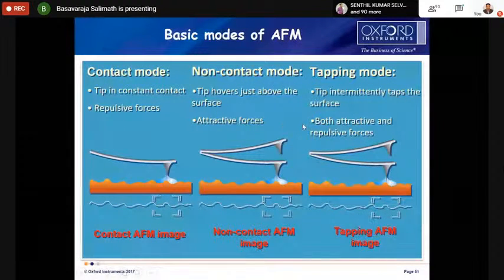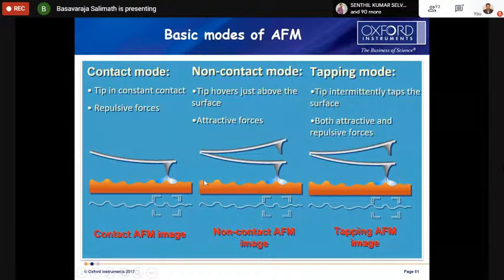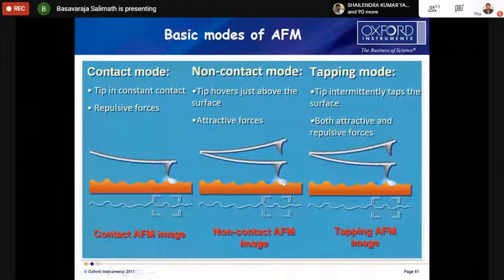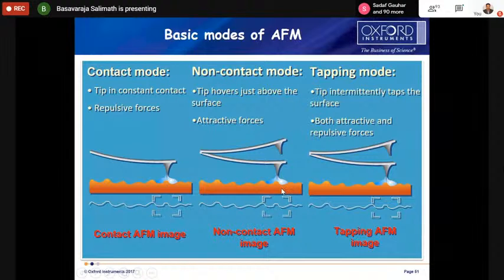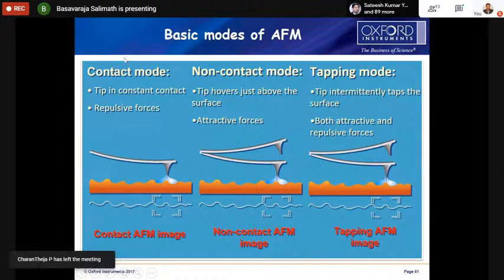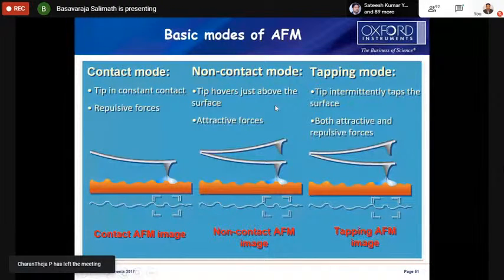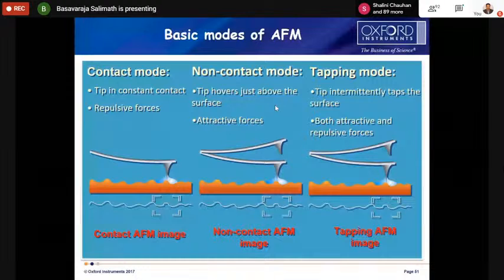Whereas in case of non-contact mode, the tip will not be touching the sample; it is maintained a little bit above the sample. So if we have some kind of water layer on the surface, we are actually getting the image of the water layer. Okay, so not the surface actually. That is one drawback of this non-contact mode, and that's why people mostly use tapping mode and contact mode. This non-contact mode is very good if you're working in a vacuum. So these are the main basic modes of the AFM.